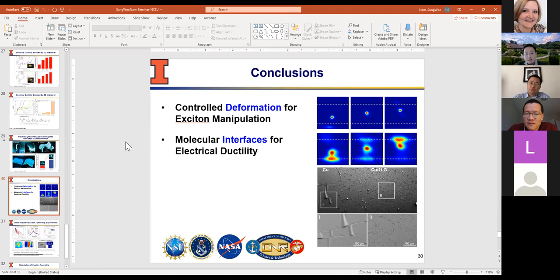And in our case, from a fabrication point of view, we just wanted to be more consistent or more conventional, in the sense that if you look at how industry does this, they basically grab a foil and polyimide, for example, and just roll it across. That's how they bond them, sometimes with some adhesive. So we thought, if we can do this with a graphene layer in the middle, maybe we can make that process relatively robust. And PDMS is something a lot more researchers are currently using for future, more conformal electronics applications. So that's the reason we started that way. But of course, there could be a way to control these structures with intentional deformation, which I think is still a very interesting way.